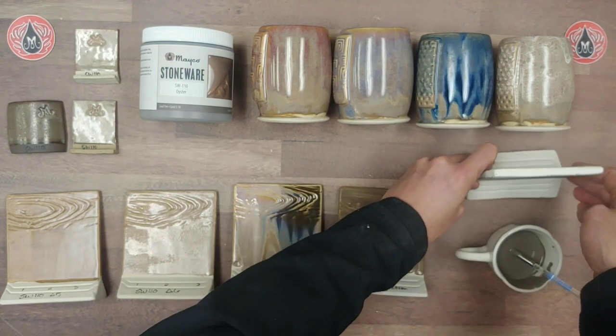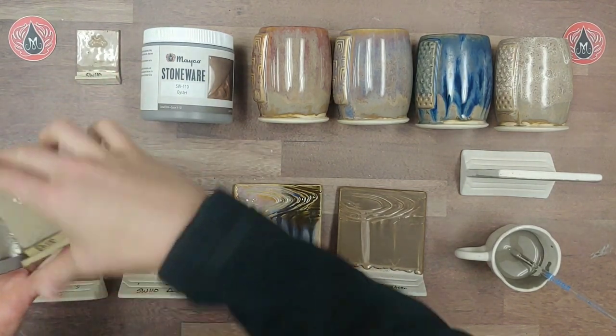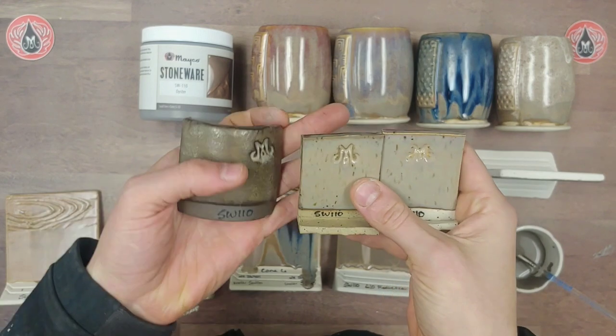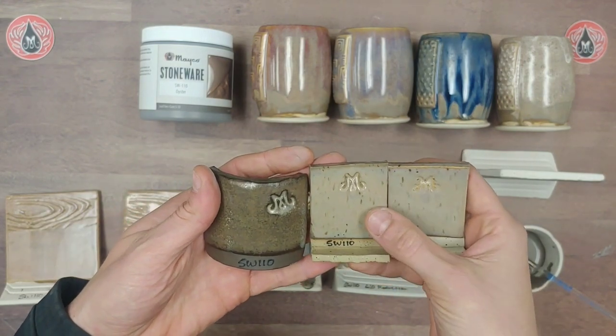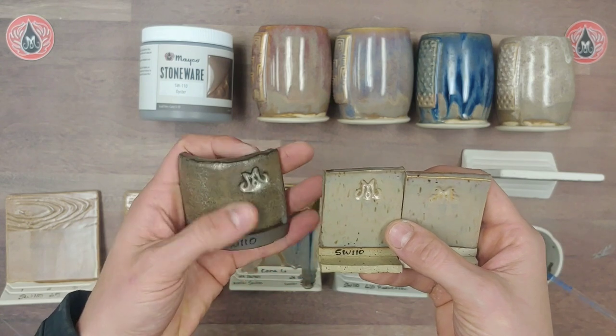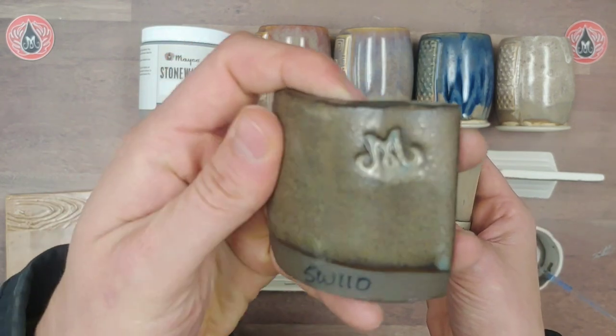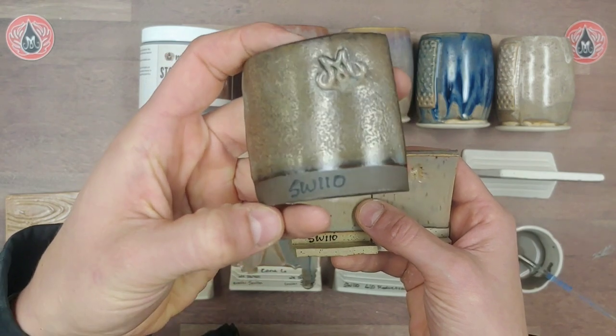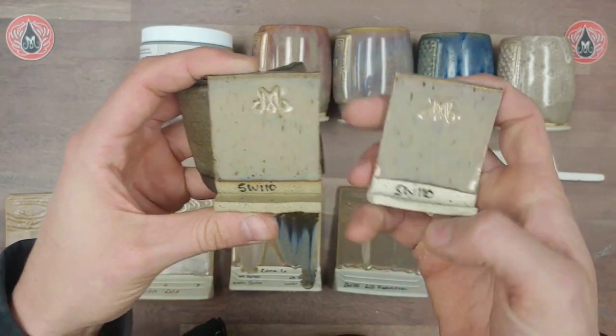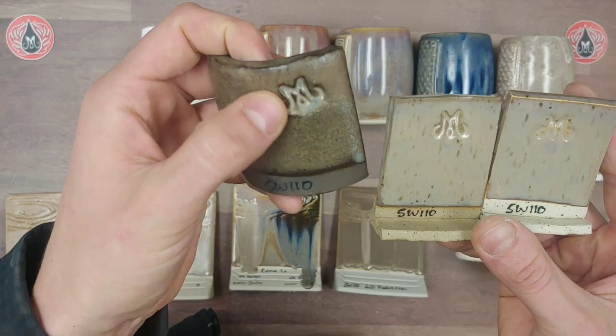I could put a coat on if I was rushing but I've got time so I'm going to wait. We'll go over our alternative clay bodies. These were all fired to cone 6 with a drop-hold and a slow cool. On the lighter or brown speckled clay we could maybe get away with just a hold, but the slow cool seems necessary. You can see the texture — it is still very smooth though, a little bit matte but no real surface issues, just an interesting texture. This is the dark brown, the speckled brown, and the speckled white.